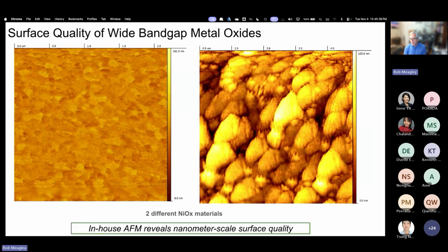However, as I said, there are other ways of creating nickel oxide coatings. On the right, we see a different nickel oxide that has a very dramatically different surface. And I have to admit, I was surprised when I started to tune the instrument to this surface. The results, at first, I was hesitant to believe that I was looking at a porous material. Nonetheless, yes, indeed, you're looking at what look like porous flakes on this surface.